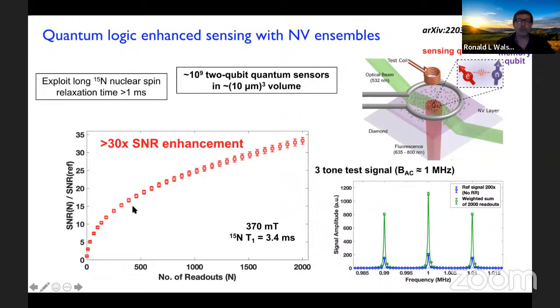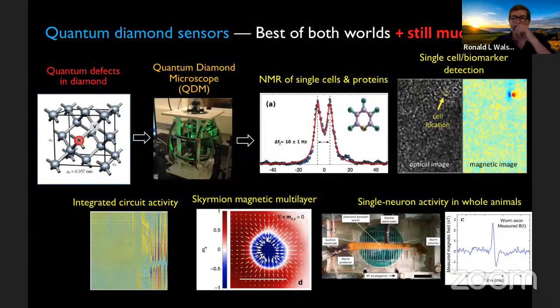We did this in a fair way where we were taking the same amount of total experiment time when compared to traditional measurements where you don't do this quantum logic enhanced technique. In green, we show a spectrum here where we applied a test signal with 3 spectral peaks. Green is the detected spectrum that we get from the quantum logic technique. Blue is if you don't use quantum logic, and we've actually multiplied the measurement by 200x. You'd have to reduce the blue by 200-fold to compare it to green. So green is clearly a lot better. That means the quantum logic technique works, and we'll be applying it now to applications such as NMR of single cells.